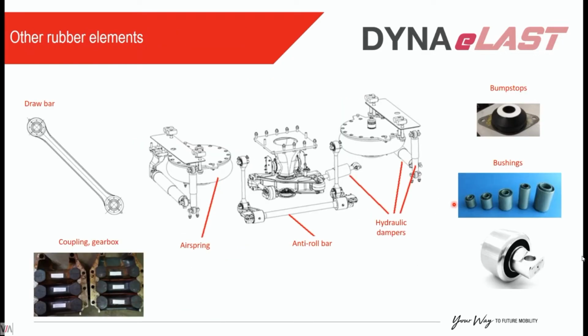Other rubber elements on the bogie, a very frequent one are the bushings. So we have a lot of articulations, and most of these articulations have rubber components there. It tends to be a problematic part because of very limited space and very high loads. Tends to fail, and bump stops, which are very critical also to ensure that we are within the envelope of the train when it comes to gauging, that it doesn't exceed the maximum displacements. So these are also critical elements. These ones in particular, sometimes from a safety point of view as well, they might be crucial.